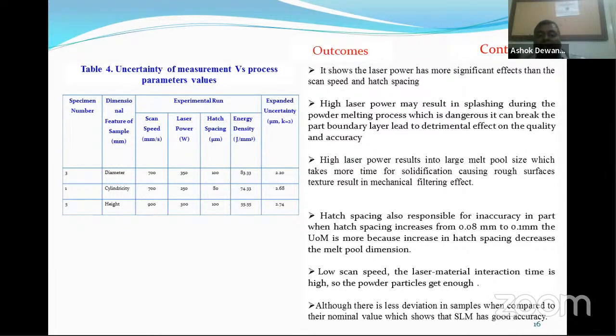So similarly, hatch spacing is responsible for inaccuracy in the part. You will see it varies from 0.08 mm to 0.1 mm. Uncertainty of measurement is more because an increase in hatch spacing decreases the melt pool dimension. At low scan speed, the laser-material interaction time is high, so the powder particles get enough time. Although there is less deviation in samples compared to their nominal values, which shows SLM has good accuracy, still I believe a difference of 0.1 mm is not very small.